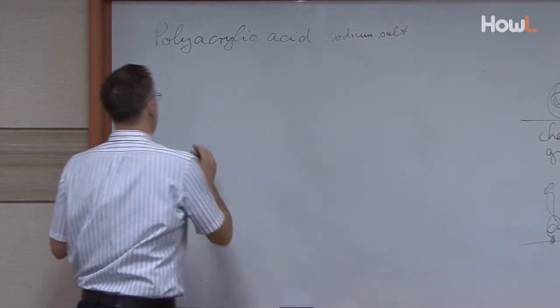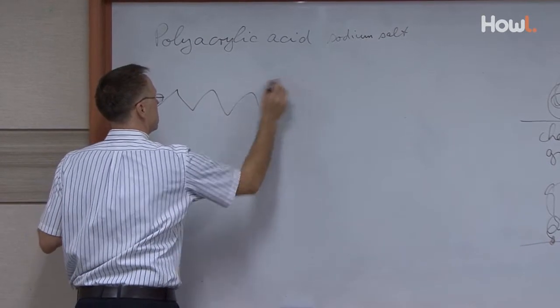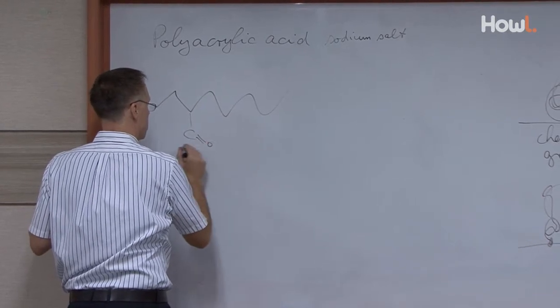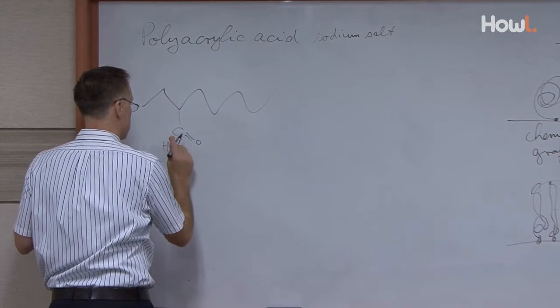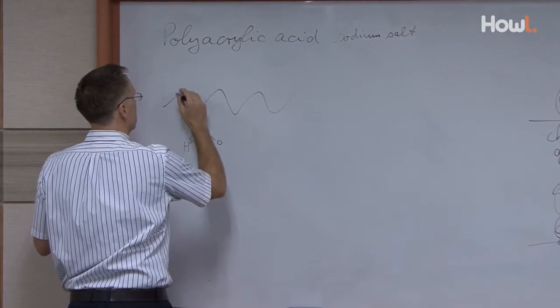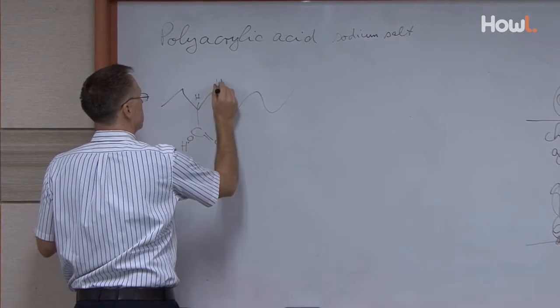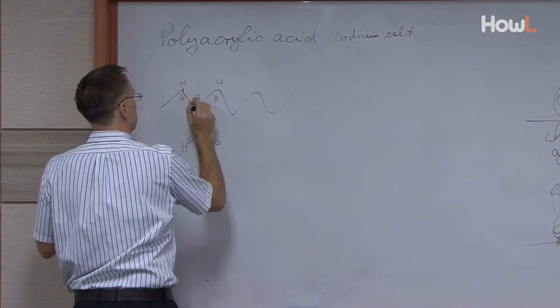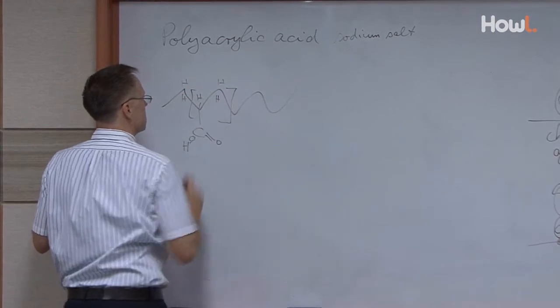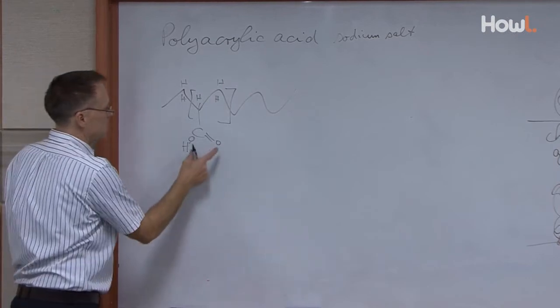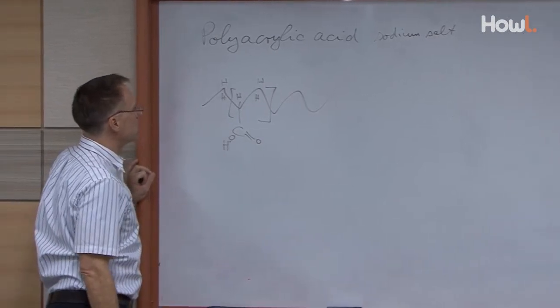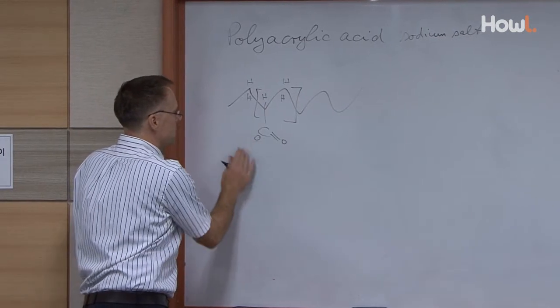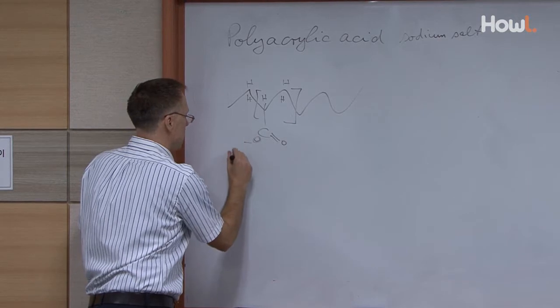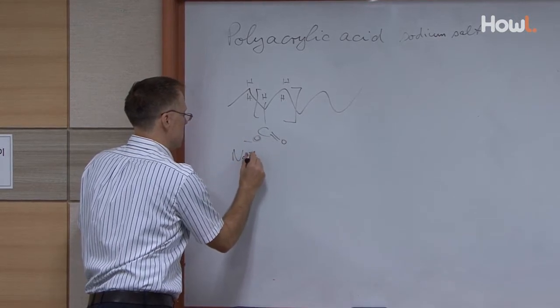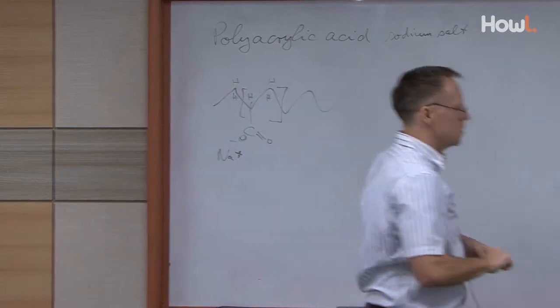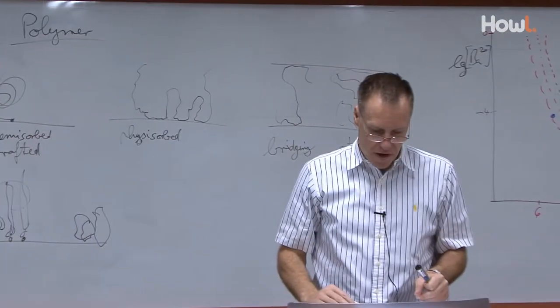So the key groups in polyacrylic acid is basically you have a backbone chain like this, and then you have side chains with an acrylic, with a COOH acid function here. And here's, of course, a hydrogen attached and so on, yeah, and hydrogen, hydrogen. The same thing, yeah? And of course you have then a repeat unit here, like this. And this is a possibility for a good dispersion, and typically we said sodium salt, so this hydrogen is actually gone. You have just COO minus, and then you have sodium plus here as a counter ion. Yeah? And this is used widely.